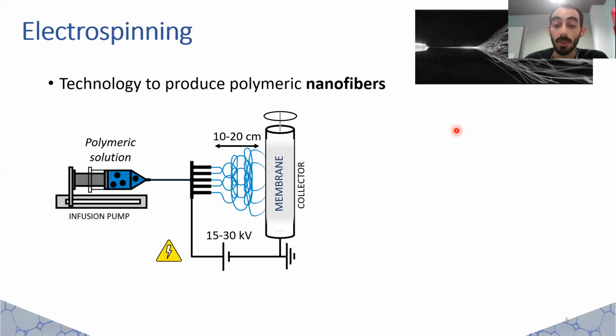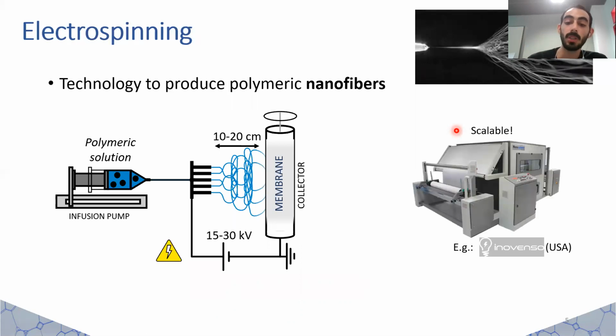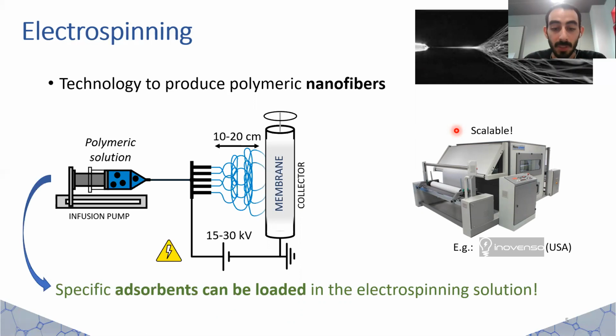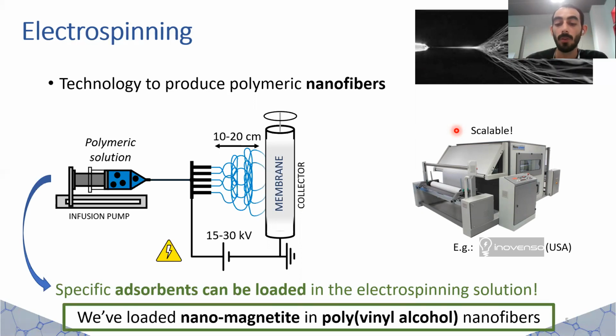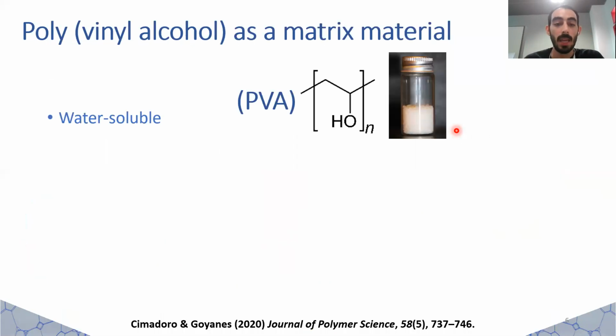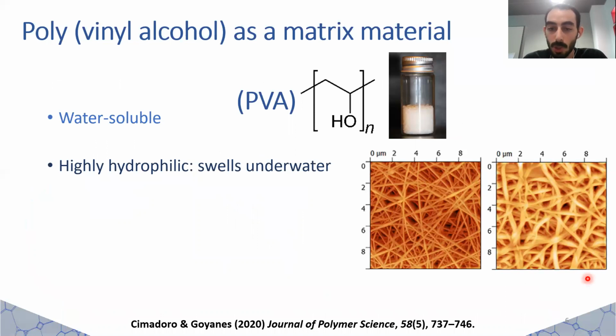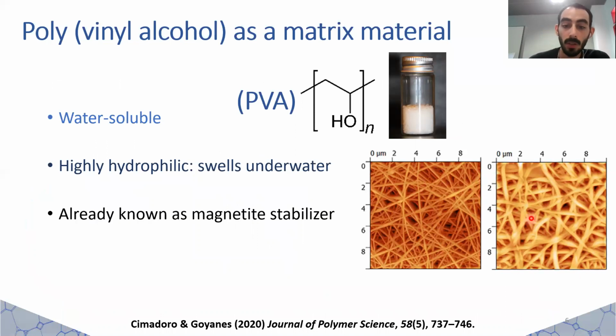This is an emergent industrial technology, as it gained special attention for the fabrication of air filtration devices like masks for the COVID-19 pandemic. Specific adsorbents can be loaded in the electrospinning solution. So in our work, we've loaded nano-magnetite in PVA nanofibers in order to produce membrane-like arsenic adsorbents. We chose PVA because it's a water-soluble polymer that swells underwater, like can be seen in these AFM images. Moreover, it is already known as a magnetite stabilizer, and it is biodegradable.